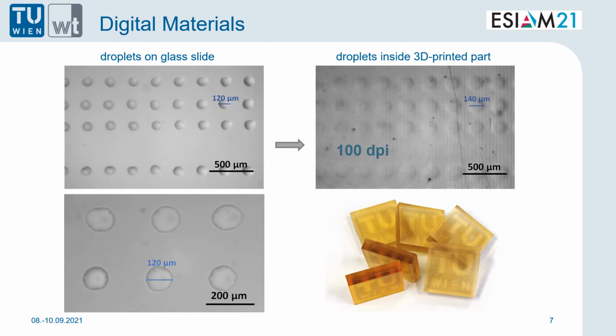With this first hybrid system, it was possible to achieve the very first modified stereolithography parts. You can see ink droplets on a functionalized glass slide on the left-hand side, and droplets of the very same ink inside of a 3D printed part. And as you can see, size, positioning, and resolution are reproducible even when jetted in the very volume of the part, as you can see here.